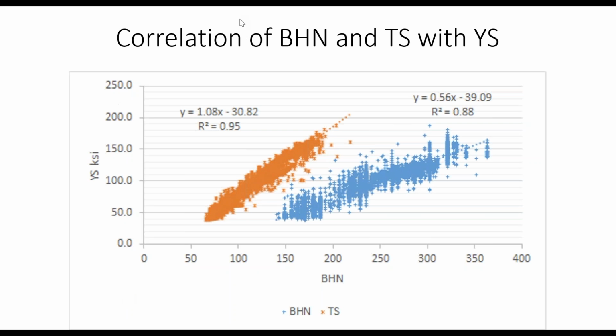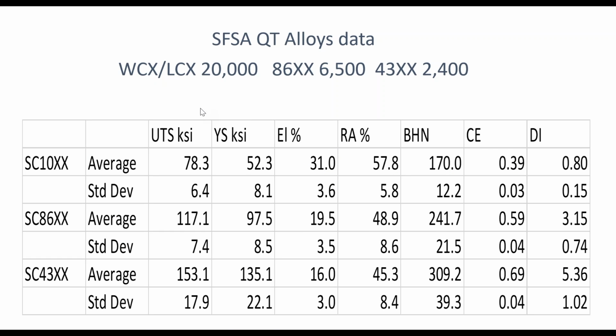So this is the correlation of our data set, the Steel Founders data set of Brinell and tensile strength with the yield strength. So I'm looking at what the yield strength is at a particular Brinell hardness or a particular tensile strength. And you can see how tight our large data set is. I get a 95% correlation and a slope of almost 1. It's 10% higher than 1 with yield strength. And yield strength is typically about 30 KSI below ultimate strength. And for Brinell hardness, I get almost 0.5. So this is the data set we have.